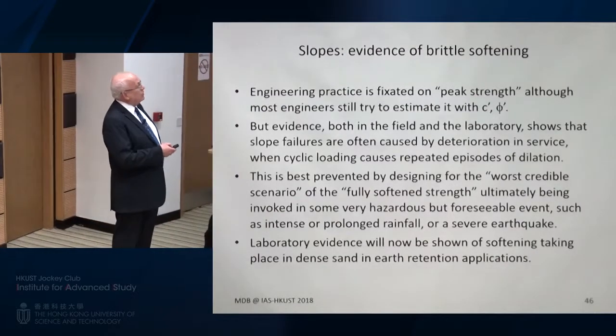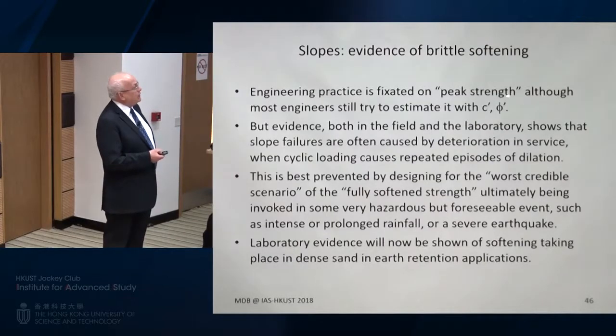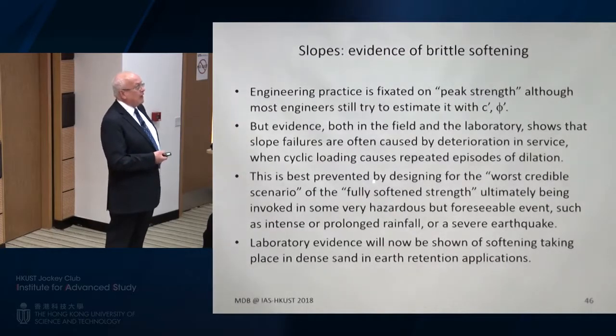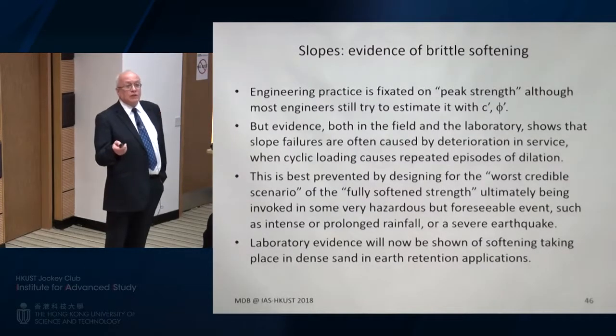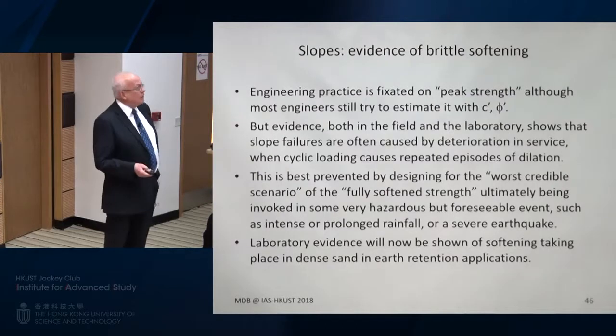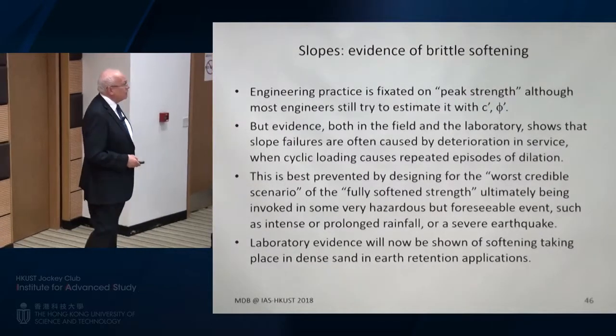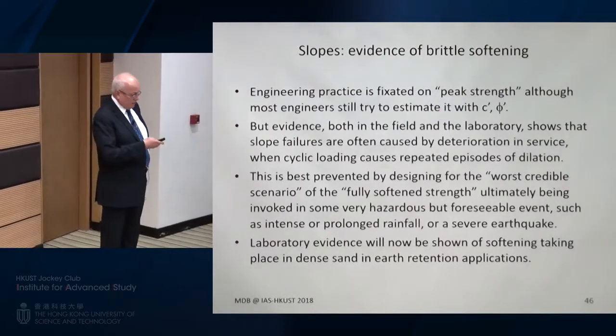Slopes: there's evidence of brittle softening in either sands or clays. Take, for example, the 1957 paper by Skempton on London clay, which showed you could only reliably mobilize phi crit, the critical state value, even though it's a very heavily over-consolidated clay.